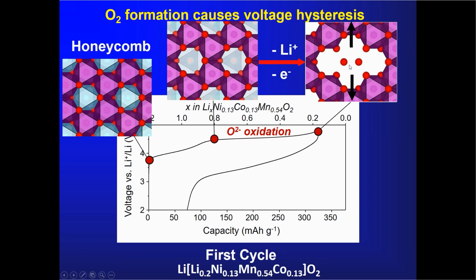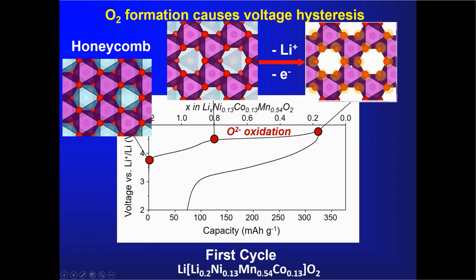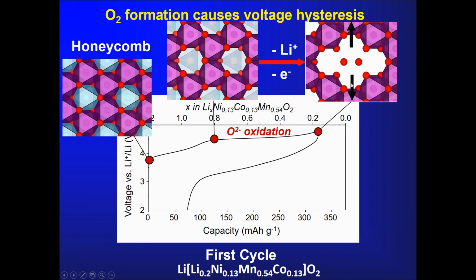And as we do so, we can relatively easily, and I'll show you the DFT to support this, undergo this transition. If I go back for a moment, we get to this point, we've oxidized a number of these oxygens, we've weakened the metal-oxygen bonds, and we simply have to move 2 manganese ions, 1 hop in each case, to create this 4-vacancy cluster. And these 2 oxygens that you see here can dimerize like this to form molecular oxygen species. And of course, the driving force for this is that these covalent bonding interactions lower the energy of the system quite significantly. So you can create clusters of this type.